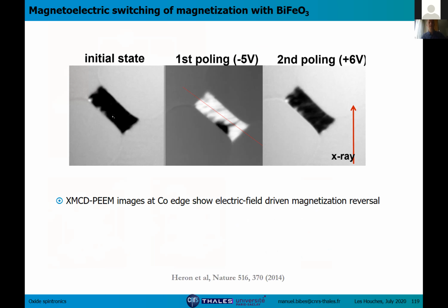So you can see that initially the magnetic domains are black, pointing in a given direction. And when you apply voltage, you are able to switch the magnetization, and you are able to recover something that looks like the initial state after a positive poling. Okay, so this is a quite good indication that it works.